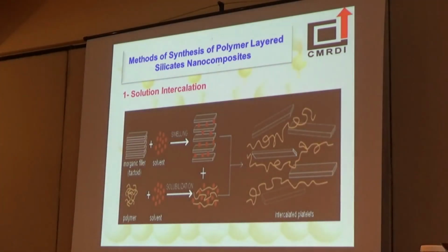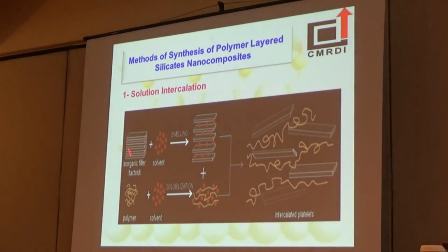Methods of synthesis of polymer layered silicate nanocomposite. There are 3 possible methods. The first method is the solution intercalation, in which the polymer is dispersed in the appropriate solvent. Then the layered silicate is dispersed in the same solution. This solvent causes swelling of the silicate layers, allowing the polymer to diffuse between these layers to form the polymer layered silicate nanocomposite.